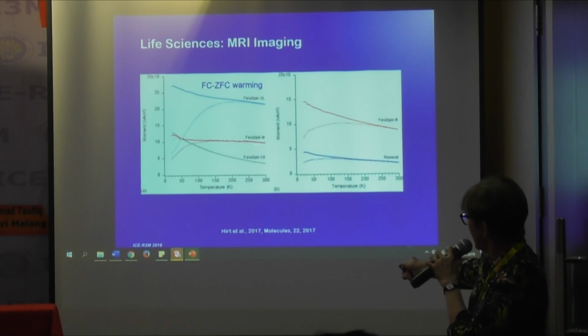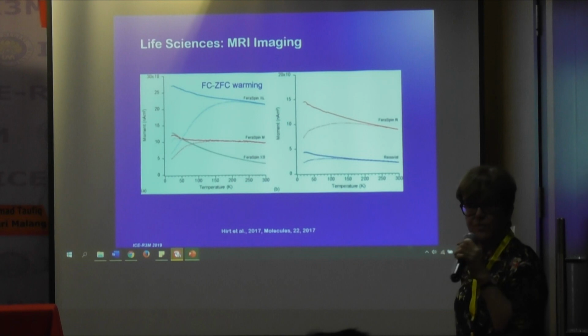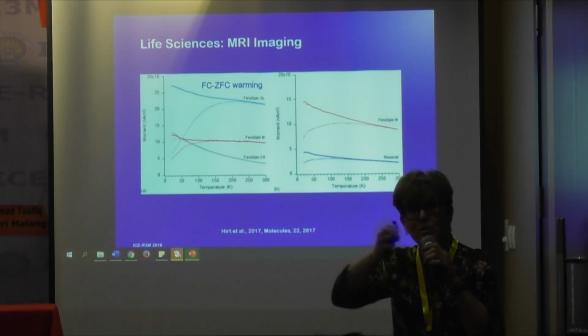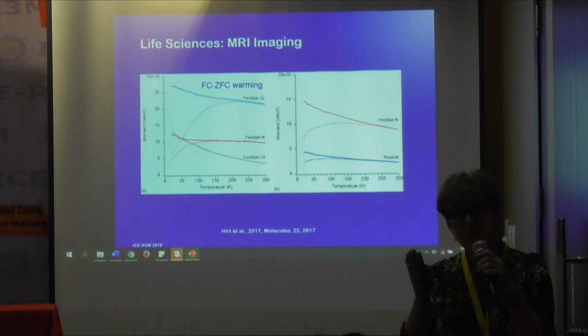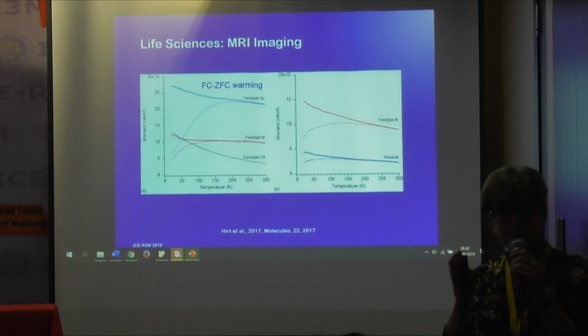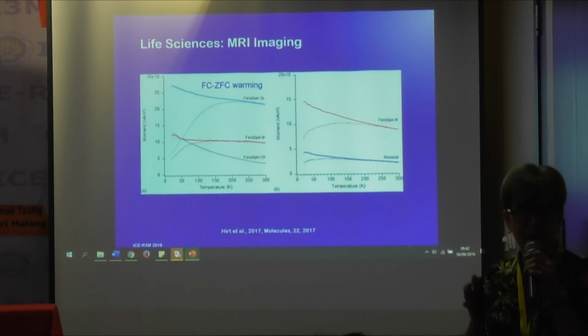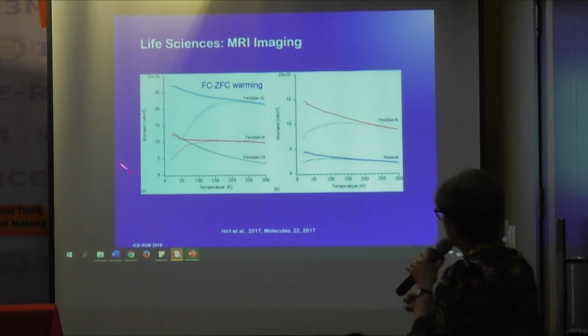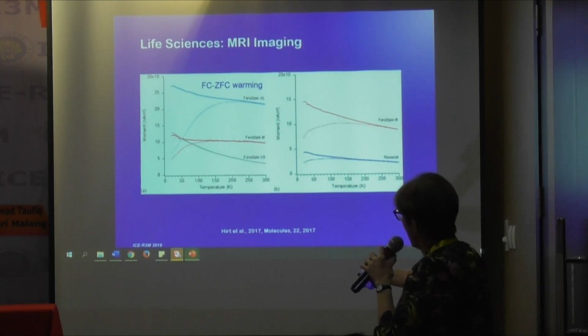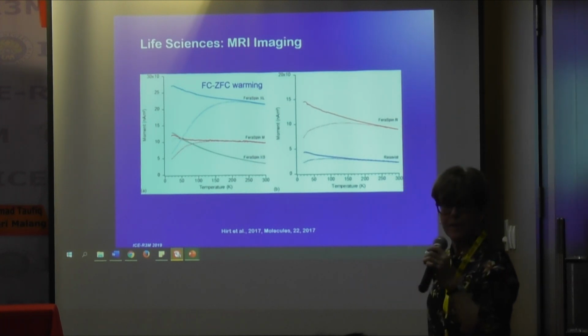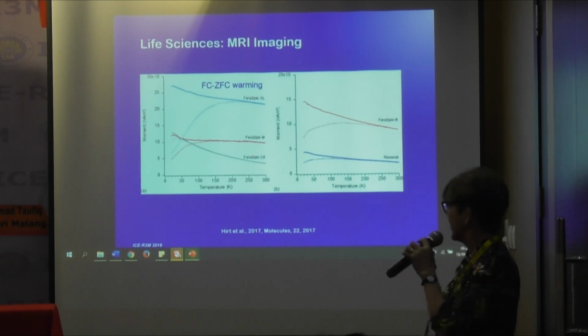When we go to the medium, you see we have to get down to almost about 160 Kelvin before they start to split. So you're only going to start magnetizing those fine grains by about 160 Kelvin. And for the very fine particles, we're almost down around 50 Kelvin before they start to undergo blocking.